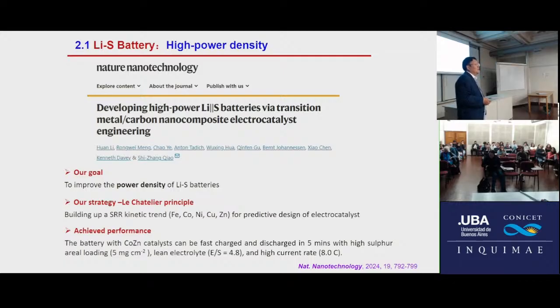But currently this battery is not available for commercialization, because its energy density is high, but power density is low. It means the discharge is very, very slow, and most of the capacity cannot be used during charge and discharge, because the kinetics is very, very low. So we must consider using a catalyst to improve the kinetics.